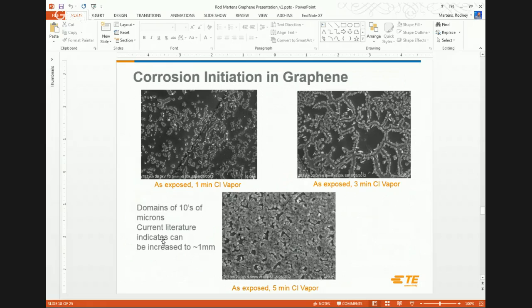These beautiful hexagonal matrices of carbon atoms are grown on a large scale film, but however you examine them closer, these domains where the hexagonal lattice is intact is usually on the order of tens of microns increasing up to a millimeter, but you could consider it as a grain. Essentially, at the edge of that, rather than having 6 carbon atoms, you might have 7. And so it's a break in the structure, and then it reorganizes into a nice grain structure neighboring to that.